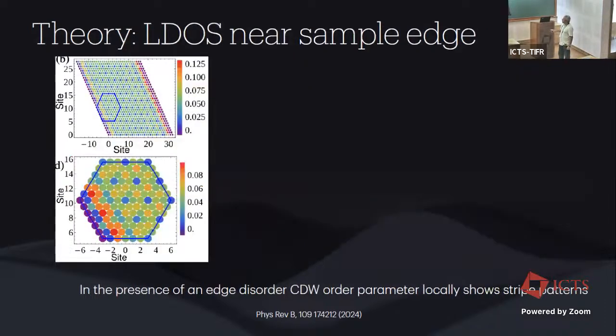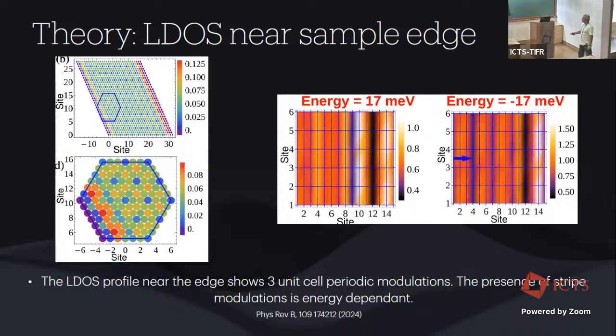So then you can also look at the stripe order near the sample edges, and what you find is effectively the local density of state shows, in the CDW order parameter it is not clear, but if you calculate the local density of state as a function of site, you can see that you clearly get these 1Q type of stripes forming, and in fact they very nicely show an effective 3-unit cell periodicity. And we also see that these stripe formations are quite energy dependent. You can get to an energy regime where you retrieve back your 3Q type CDW order.